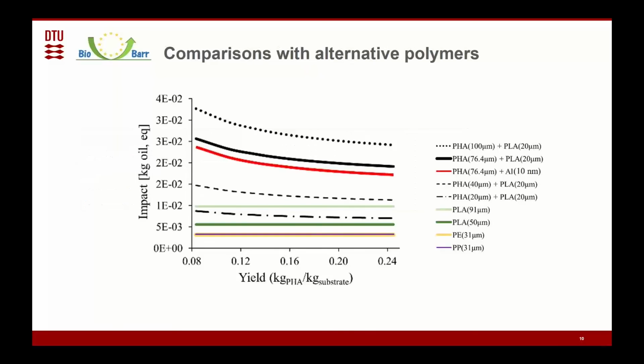Now, perhaps the most interesting set of results: comparison with alternative polymers. So what you can see here is the impact for PHA, different thicknesses, different ways of functionalization, as they depend on the yield of PHA from the feedstock. So the higher the yield, the lower the impact. This is for the use of fossil resources. And we wanted to see how it compares with fossil-based polymers like PE or PP, but also PLA.